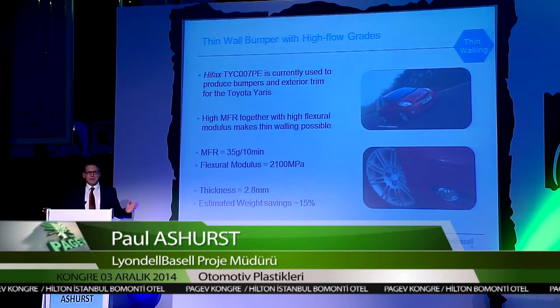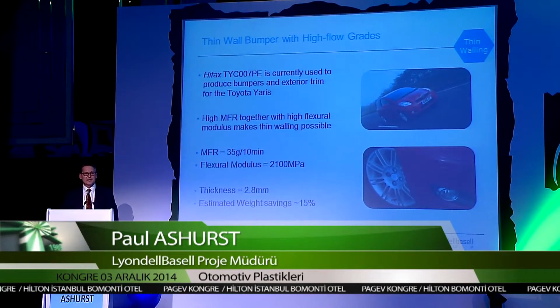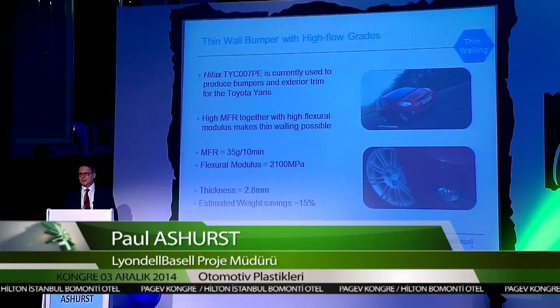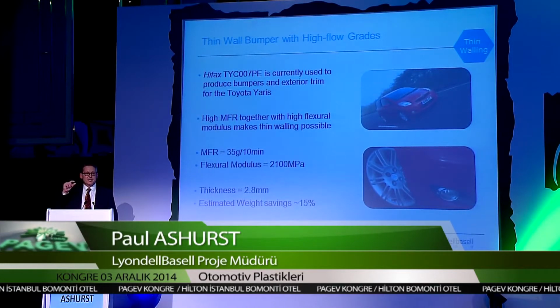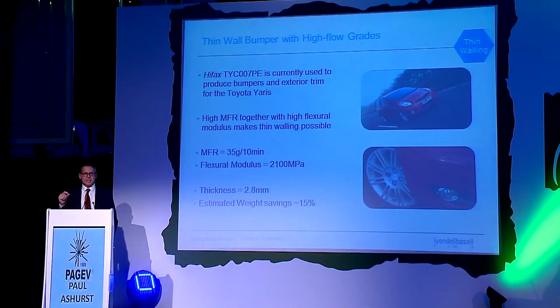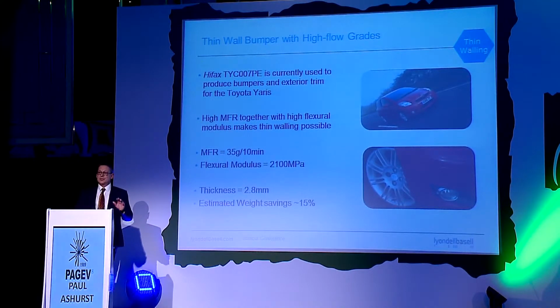Toyota, and indeed the Japanese OEMs, have been the pioneers in thin walling or down gauging. Of course, if you reduce the thickness of the part, you have to increase the flow of the material. And because the part is thinner, it means you have to increase the modulus of the material to achieve the same relative rigidity. We supply this material directly to Toyota France for the Yaris bumper. It offers weight savings of about 15% compared to conventional talc fill materials. We're also supplying this material extensively here in Turkey for the Toyota Verso and Corolla sedan exterior trim parts.